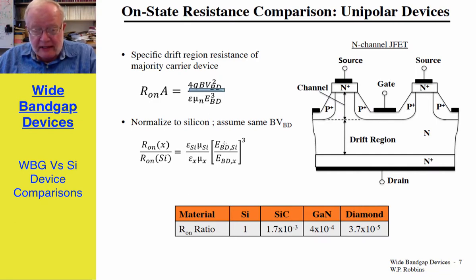If we normalize that to silicon and assume the same breakdown voltage for all types of devices, similar devices made out of the 4 different materials, the on-state resistance ratio in silicon is 1. Silicon carbide is about 10 to the minus 3. In gallium nitride it's 4 times 10 to the minus 4, and in diamond it's 4 times 10 to the minus 5. Again showing why the breakdown field strength is the most important thing in determining on-state resistance and thus